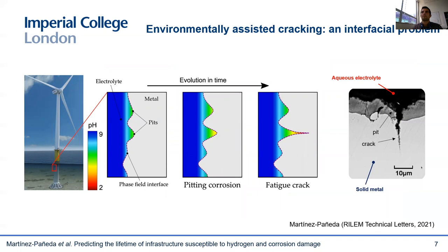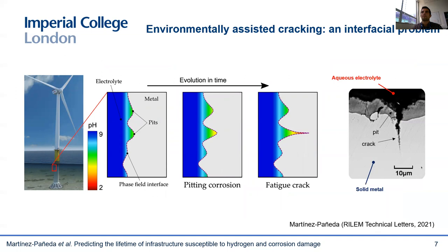But there's a second, arguably bigger challenge from the modeling perspective. Environmental assisted cracking phenomena are essentially interfacial problems. You can see in the slide an example of the different stages involved in the corrosion fatigue of wind turbine support structures. First, we have pits that nucleate at the seawater-metal interface. Then those pits grow, and eventually we see a pit-to-crack transition and the propagation of fatigue cracks. So the morphology of the interface is consistently evolving and capturing this is key.